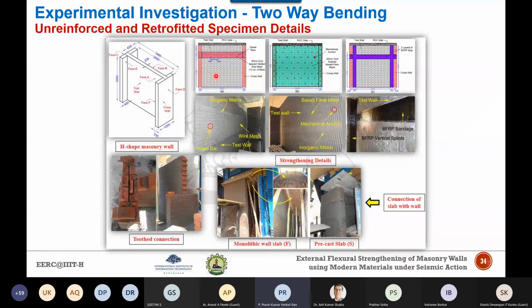And the dowel bars have been used to connect the masonry and this welded wire mesh to ensure a composite action or to transfer the shear forces at the interfaces. Now, this horizontal bandage, what it is doing is, it is integrating the orthogonal walls and supporting the main wall, especially in the out of plane direction. Okay, especially in the out of plane direction.